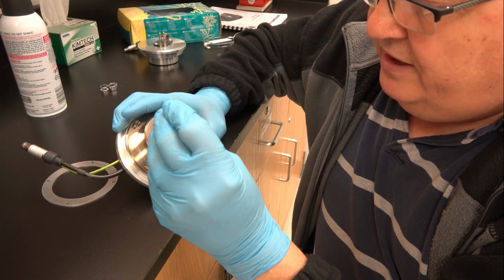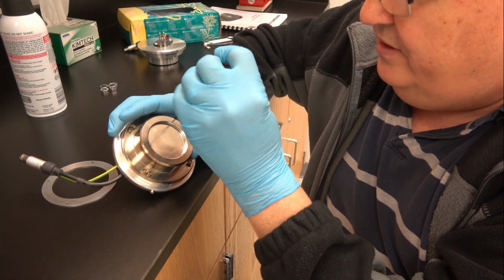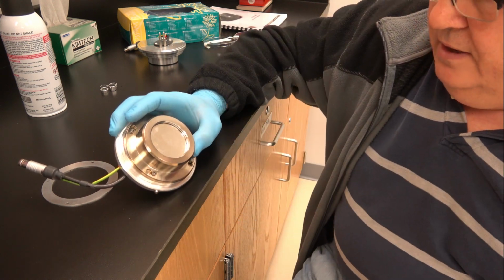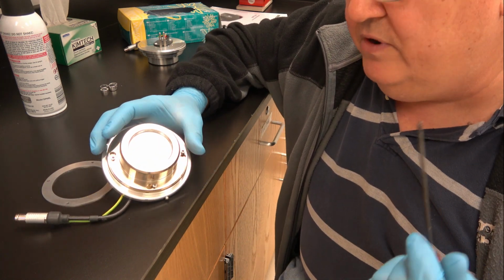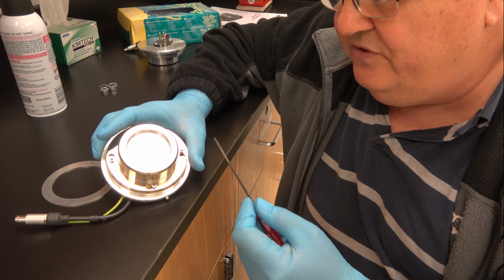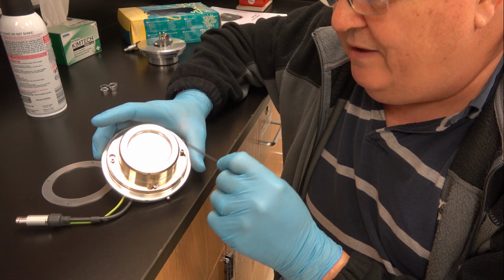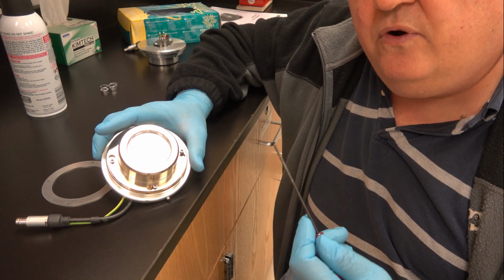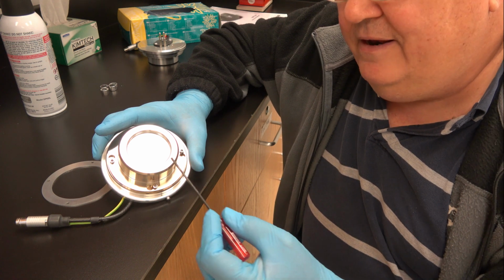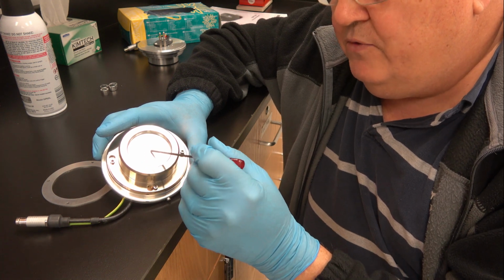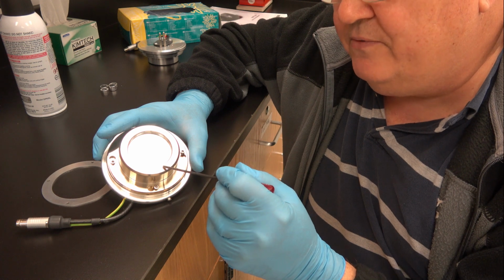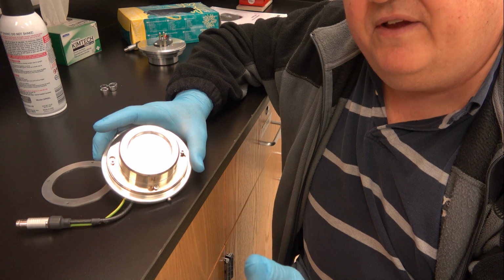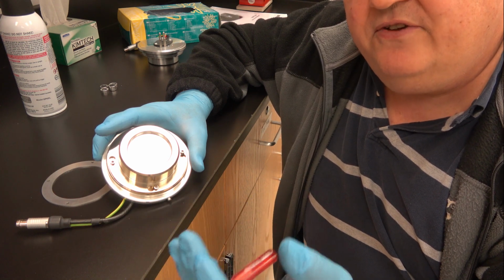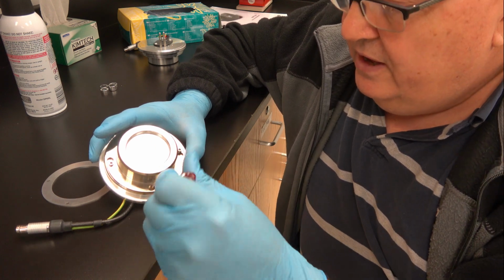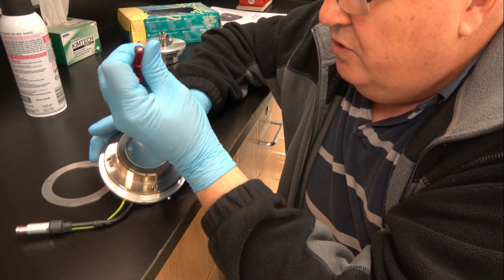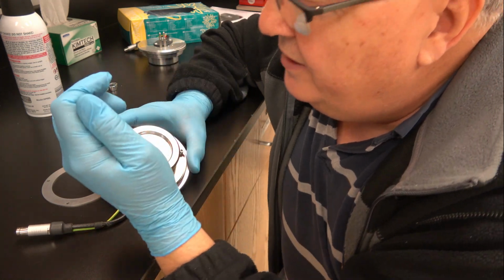Okay, so what if you've done all this and you still have a short condition indicated by the computer in the system? Well, the way I would troubleshoot it, if it happened to me, is my next step would be installing the insert without the dark space ring and test it. If your short condition goes away, well then there's something still contacting between the target or target retaining ring and the dark space ring. Removing this removes the dark space ring from the equation and any possible short condition on the sputter head, with the exception of the sputter head has a fault which would require sending the sputter head to me.